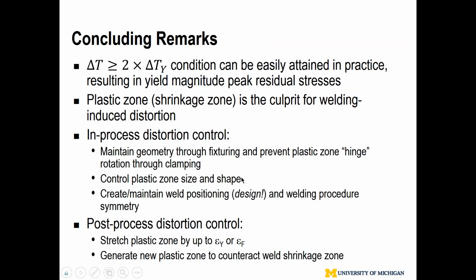So I use multiple pass welds, you use clamping, and even though you don't have the symmetry, in that case you can implement procedure symmetry. So if this in-process approach doesn't cost much, and the post-process is still not good enough, that means what is causing residual stress is yield magnitude, because epsilon Y or epsilon F, that's yield strain or flow strain, gets produced in the plastic zone or shrinkage zone. Whatever you can do to stretch it, okay? That's why with hammer peening, you don't stretch, you compress it, so you get elongation in the lateral plane, and you can reduce it. You don't need to introduce too much. And sometimes you can introduce a new plastic zone to counteract the weld shrinkage zone.